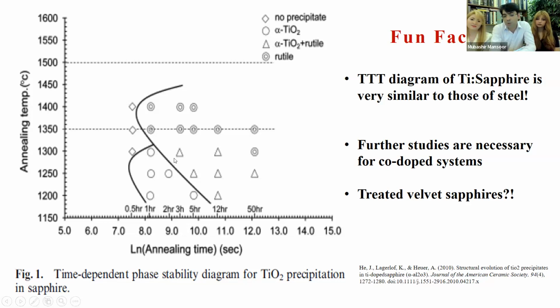The same kind of observations we have also for sapphire. So if you, for example, dissolve all of the rutile, but you reduce your temperature very slowly, then all of that excess rutile that you dissolved suddenly reprecipitates, reappears in your sapphire. So that also makes it very important to cool down your sapphires from high temperature very quickly. Otherwise, if you don't quench them, as we call it, by quench, it means cooling it down very rapidly, you would get these reappearing.